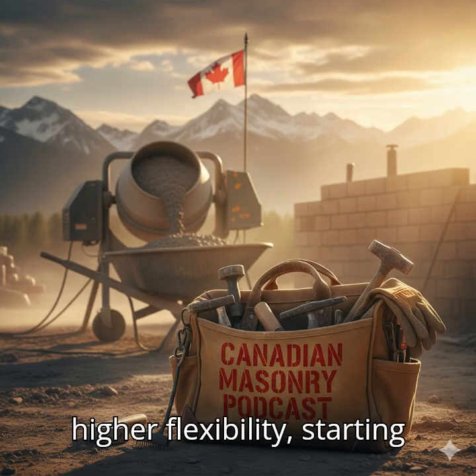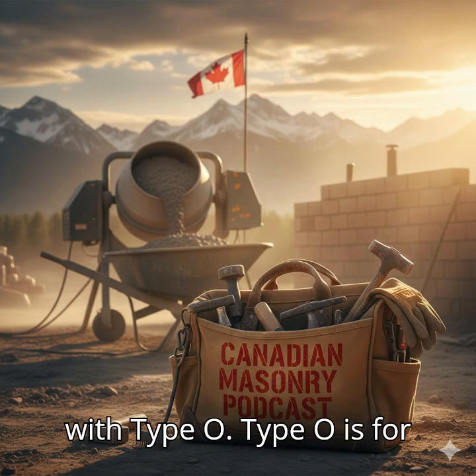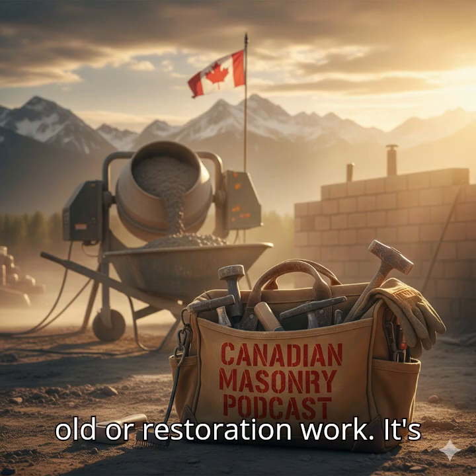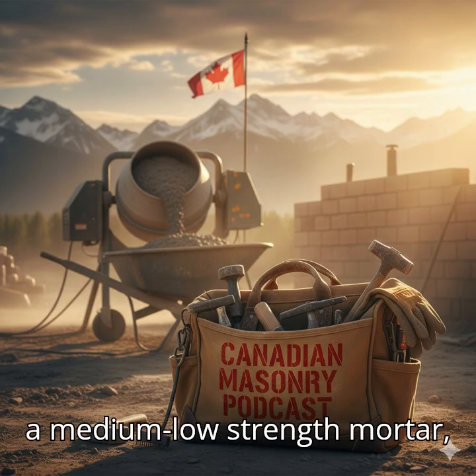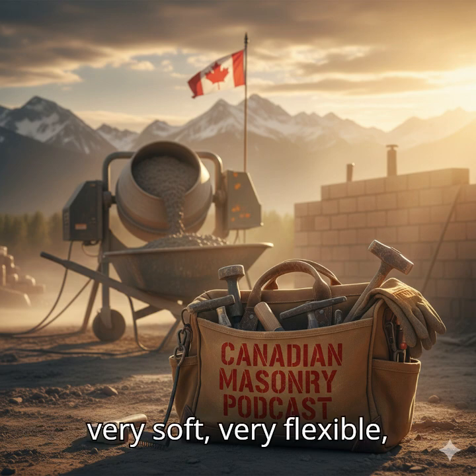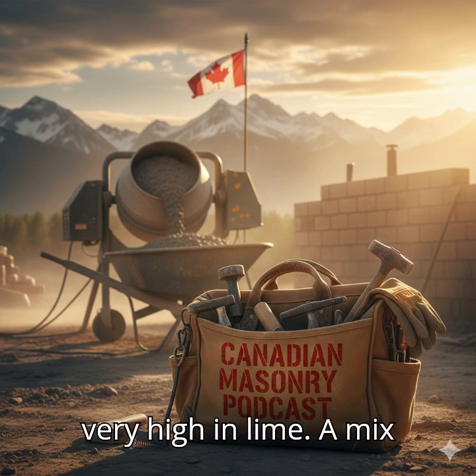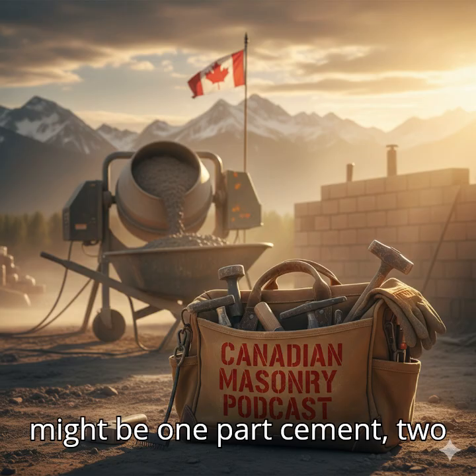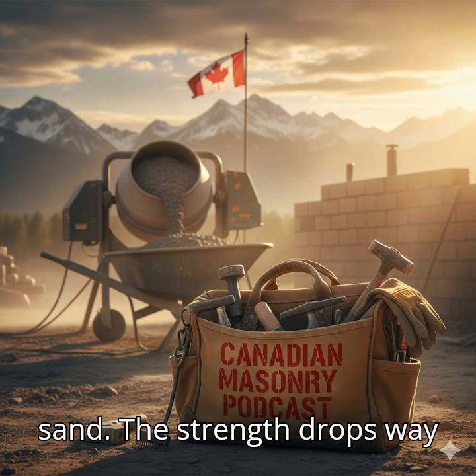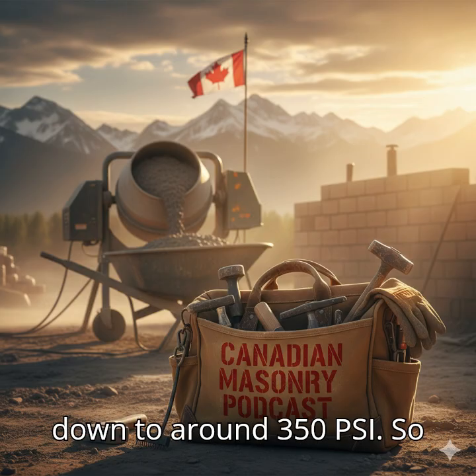Okay, now we're moving into the specialty mortars. Lower strength, higher flexibility, starting with Type O. Type O is for old or restoration work. It's a medium-low strength mortar, very soft, very flexible, very high in lime. A mix might be 1 part cement, 2 parts lime to 9 parts sand. The strength drops way down to around 350 psi. So why on earth would you ever want a mortar that weak?